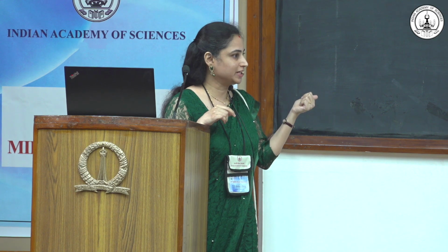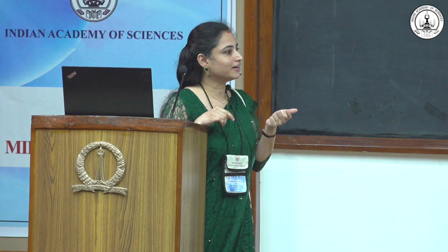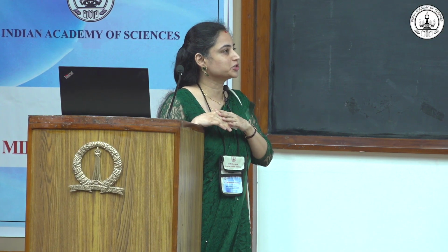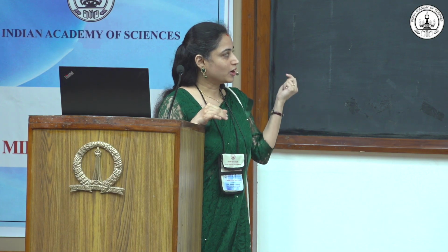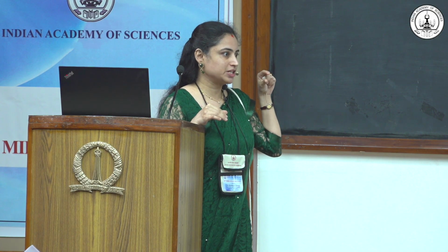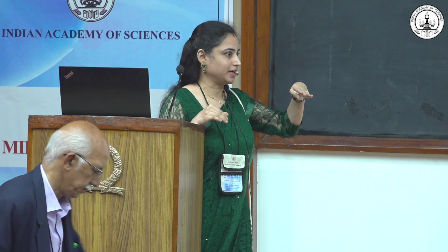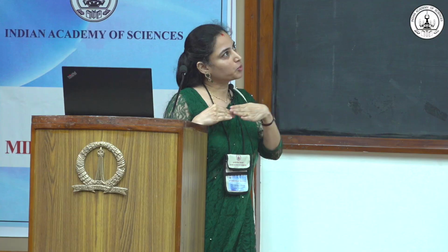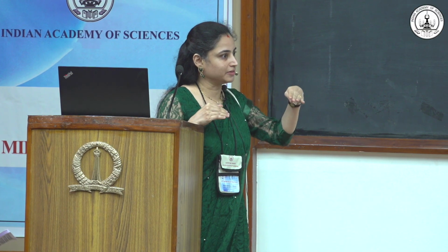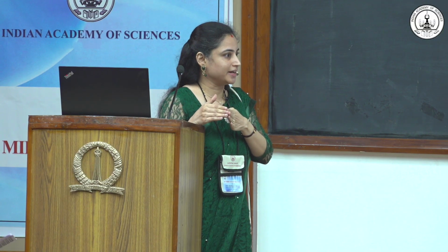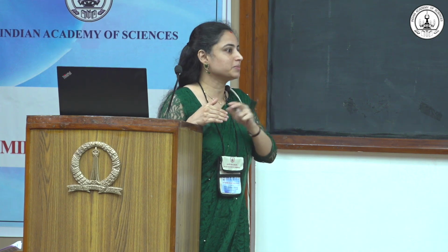Because in case of tin telluride, for about 800 Kelvin, in order to stop the bipolar diffusion, we need a band gap of around 0.4. In case of SnTe at room temperature, the band gap is 0.18. If we consider the temperature effect, the band gap opens something around 4 times 10 power minus 4 eV per Kelvin, so it will be around 0.38. Still it does not reach 0.4, so there will be bipolar diffusion.